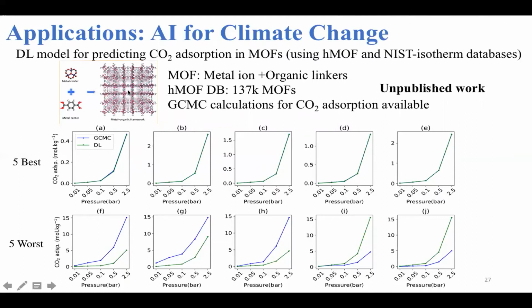And there are pores, and there are materials such as zeolites, which are traditionally used for carbon capture, but metal organic frameworks are extremely promising because of the high functionalities. And there have been databases such as hMOF, the hypothetical metal organic framework database, which has around 137,000 MOF materials, and they also nicely provide the grand canonical Monte Carlo simulation for CO2 adsorption. And in fact, this GCMC for CO2 adsorption compares well with experiments.